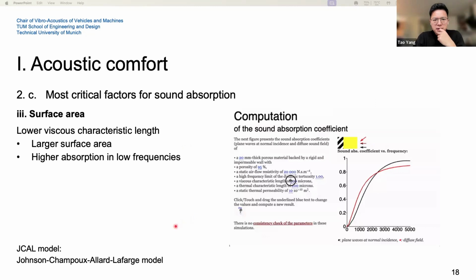And here is the JCA model, numerical modeling. I changed the parameter of viscous characteristic length, which is related to the surface area. Lower viscous characteristic length means higher surface area. So if we lower the value from around 1000 to around 10 or 5, we can see the best sound absorption shifting to low frequencies. That's what we want to see.